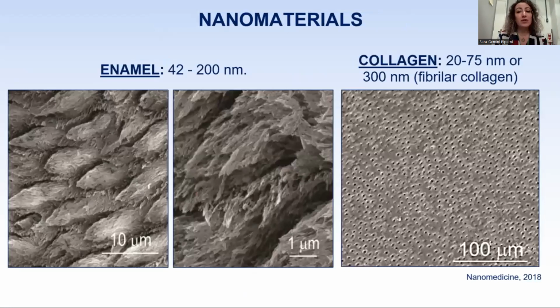And biomaterials behavior is strongly influenced by the physical chemical properties, and often this depends from material size. So the body tissue are composed of nanostructure, as demonstrated here in these images that are dental micrographs from electronic microscope. For example, the dental enamel is 42 to 200 nanometers. Collagen is 20 to 75 nanometers or 300 nanometers when it forms fibrillar collagen. So as you can see, the body tissue is composed by nanostructure. So the development of nanoscale materials is becoming increasingly attractive.